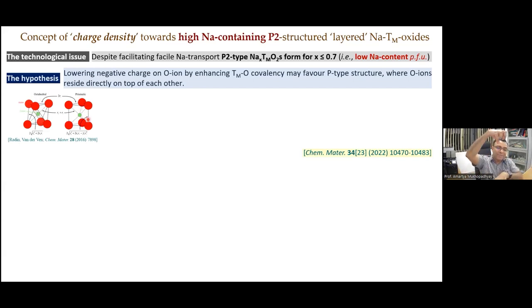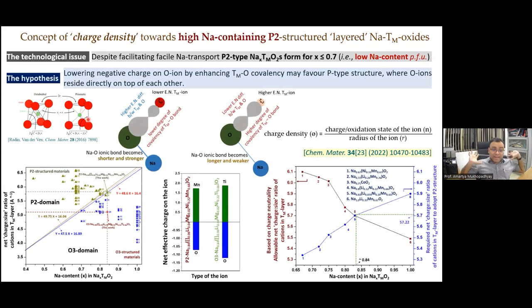So, if we can reduce the effective negative charge on the oxygen ion, we can make them sit on top of one another despite having more sodium content and having them come closer to each other because of the electrostatic attraction caused by the presence of sodium ion. So that is the concept. It's basically going back to the same fundamental concept, but for a different purpose. So now for designing high sodium containing P-structured layered transition metal oxide, we want to enhance the covalency of the transition metal oxygen bond. That is, we want to increase the charge to size ratio of the transition metal layer.